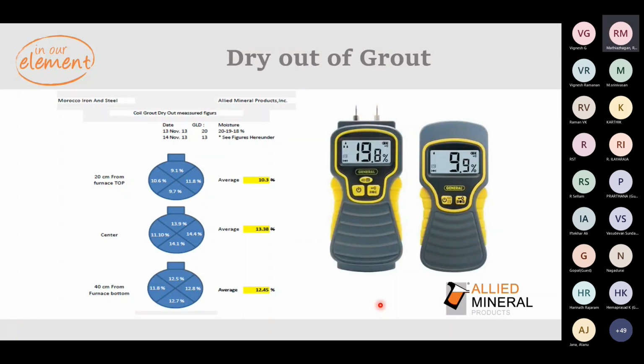So this is a slide which shows that we normally recommend using a moisture meter. This is a moisture meter which we can use to detect the moisture level in the grout. Once the moisture is below 10, the furnace is ready for lining. Some people go ahead with the GLD values also, which is again a good thing. You can record the values before the dry out cycle is started and after the cycle has been done to correlate the values and to proceed with the lining.